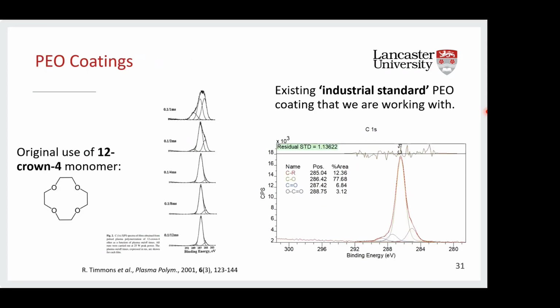So in the early 2000s, 12 crown 4 was explored by the Timmons group as an option to produce these non-fouling coatings. And these are the XPS spectra they produce. So you can see they have one peak which is clearly dominating the spectrum, and this is the peak that sits at around 286.5 electron volts, which relates to the ethylene oxide character, or this CO bond. This is what we're aiming for in our research.